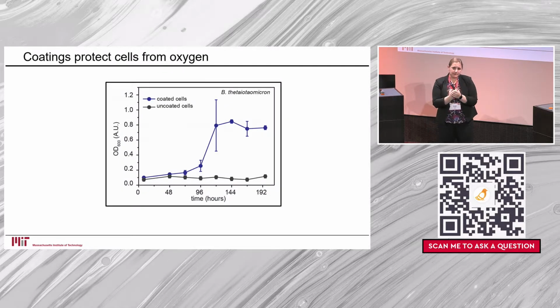We can also look at an anaerobe. So B theta, the microbe that I talked about that can be used to treat colorectal cancer, is an anaerobe, so it doesn't like oxygen. Well, we can see that for the uncoated cells, if we freeze dry them and store them under oxygen, they all die. In contrast, our coated cells not only survive, but they grow to a normal steady state within a normal amount of time. So we really haven't impacted their growth or proliferation.